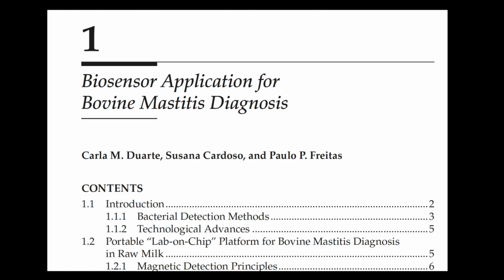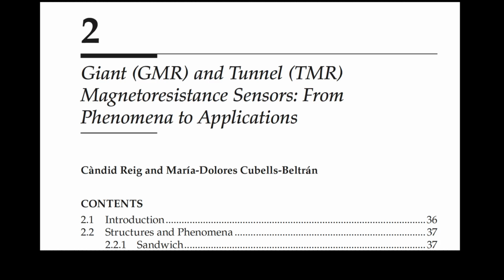Definitely. Now, moving on to the core sensor technology behind this: spin valve magnetoresistive sensors. Spin valve sensors are a mature magnetoresistive technology widely used in biosensing and other fields. They consist of multi-layer thin films of ferromagnetic and non-magnetic metals like tantalum, manganese iridium, cobalt iron, copper, and nickel iron, with nanometer scale thicknesses. The key principle is that the sensor's electrical resistance changes depending on the relative orientation of magnetization in the ferromagnetic layers. This makes them highly sensitive to magnetic fields. The active sensor areas are tiny, on the order of 10 by 2 micrometers or 3 by 100 micrometers. In biosensing, these sensors detect fringe magnetic fields from superparamagnetic nanoparticles attached to bacteria flowing over the sensor surface.